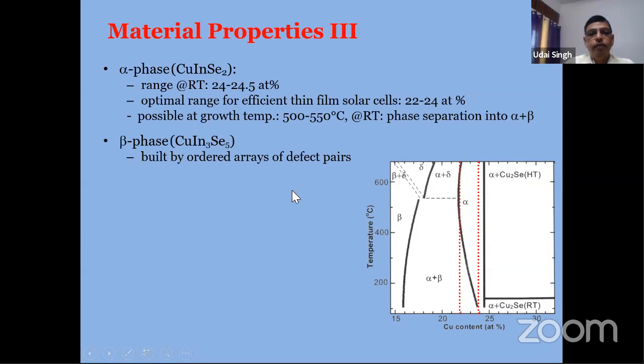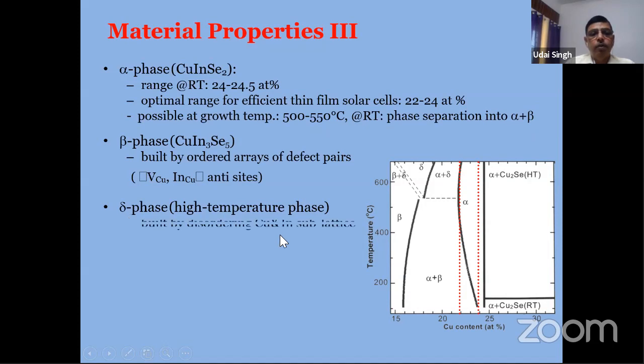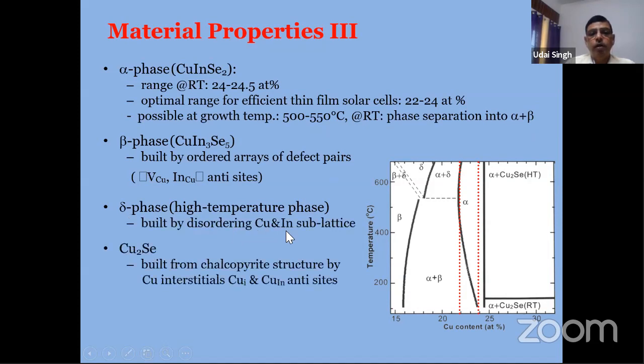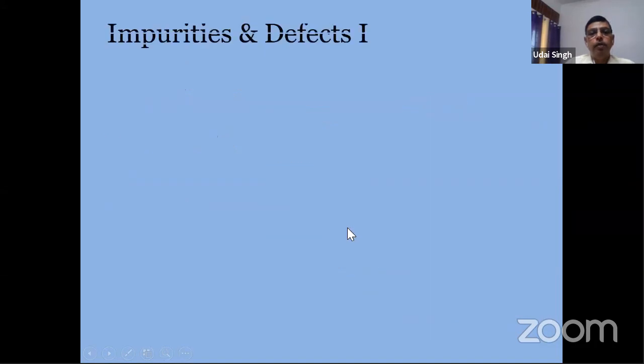Otherwise, you get the beta phase, with certain vacancies, copper vacancies, and indium replacing the copper, which are antisites. You get the delta phase also, built by disordering copper and indium. So these will create all the defect states. Now, if you go beyond 25, you get the copper selenide phase, which is basically a highly conducting material.